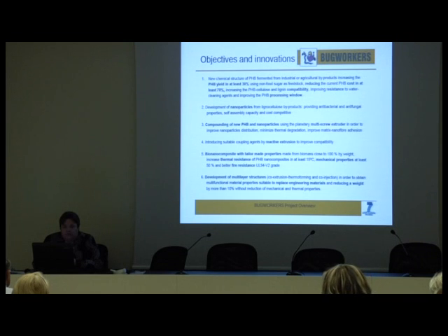The idea is to introduce suitable coupling agents by reactive extrusion to improve compatibility, and also to reach higher fire resistance and thermal resistance of the composite. For the final composite, our aim is to reach something close to 100% bio-based, but as explained by the previous speaker, as close as possible to 100%. We are not sure if it will be 98 or 95. And in the project, we will also work on multi-layer structures in order to obtain multifunctional material properties suitable to replace the engineering materials.